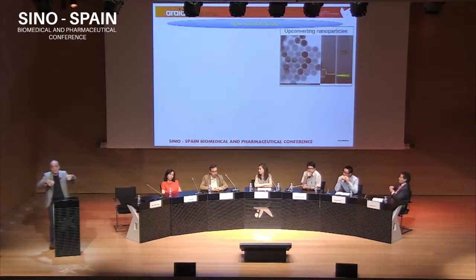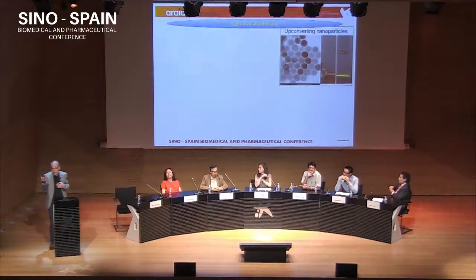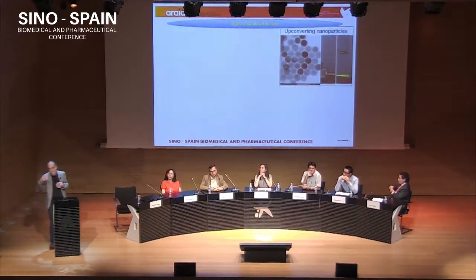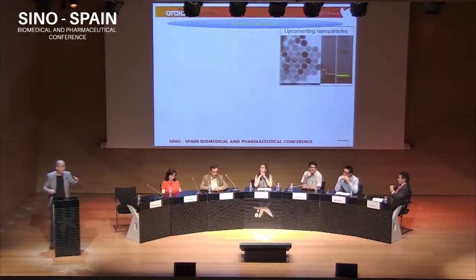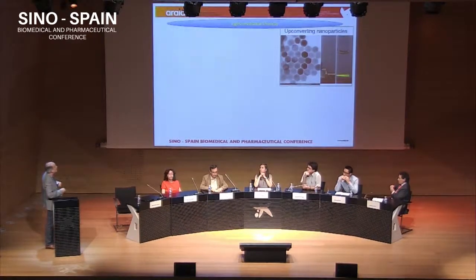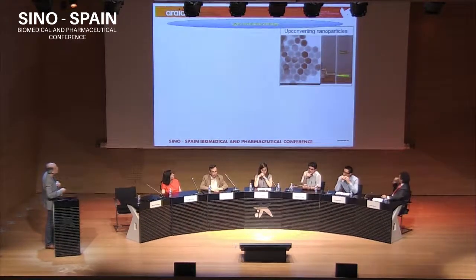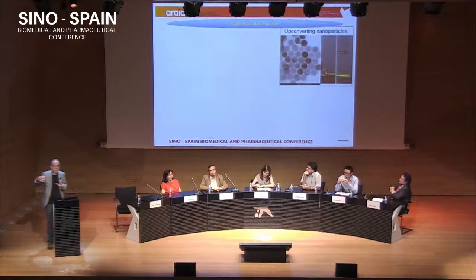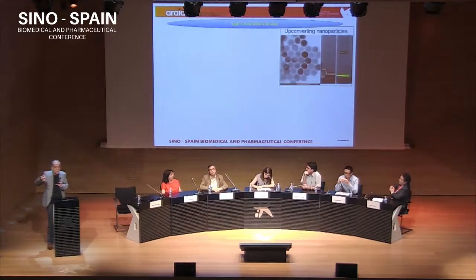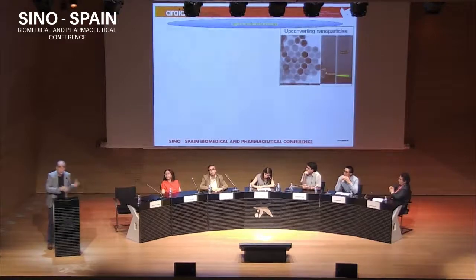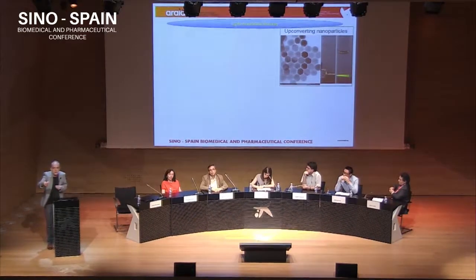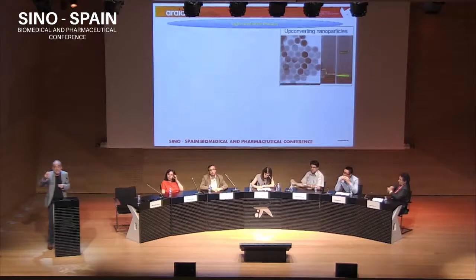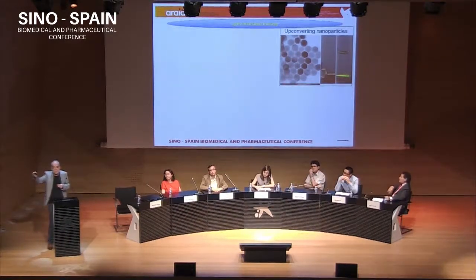So you have a synergistic effect in which you are heating the particles, you are killing the tumor by hyperthermia, but also the increase in temperature can be used to trigger the release of the drug that is in the polymer, okay? So for that, there's one more thing that you can do, which is to use upconverting nanoparticles. This means that the particles receive laser of a low frequency, for instance, infrared light, which is the most penetrating one in the body, and emit light of a different wavelength, which is more energetic and create a lot of reactive oxygen species that will kill the cells.